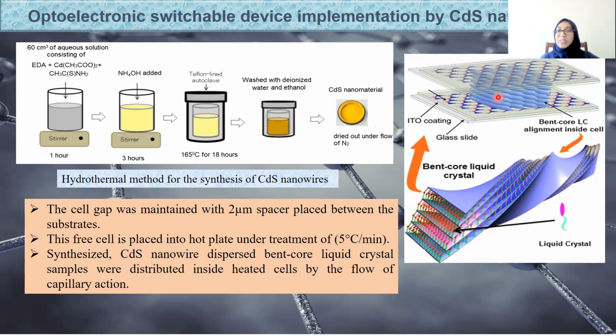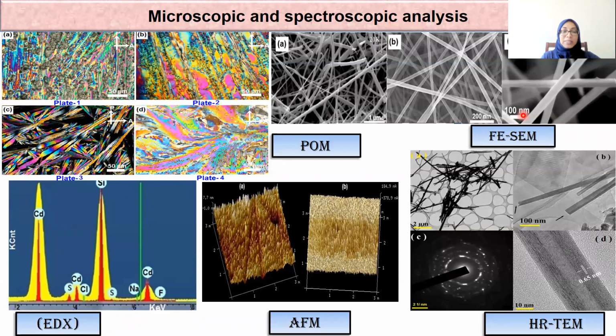Here, these are the substrates which have an ITO coating, and the cell gap was maintained with a 2 micrometer spacer placed between the substrates. Here, it was heated, and the CdS nanowire dispersed bent core liquid crystal sample was distributed inside the heated cell by the flow of capillary action.